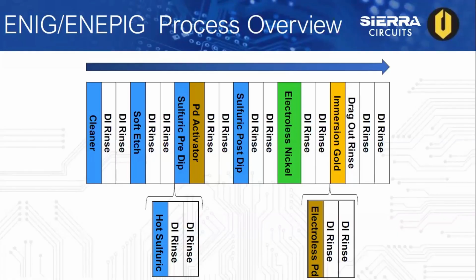Now, a hot sulfuric bath may also be implemented, as you can see on the bottom left there, especially when working with thick panels that have through holes. This way you can flush out any remaining etch solution. And really, by doing this, it helps avoid the issue of skip plating, if you haven't heard of it, which pretty much involves some areas of the substrate not undergoing ENIG or ENEPIG plating.